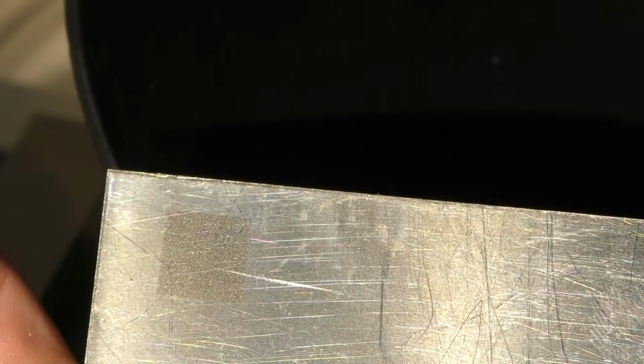Now look, I'm going to rotate this very slightly backwards and forwards, and as I rotate it backwards, it turns to black, and as I rotate it forward, I get the pattern back again, and then it turns to black. It's got a very narrow viewing angle, and that viewing angle is less than plus or minus 10 degrees. So I'm now going to go to the other extreme, and I'm going to put a 350 nanosecond pulse in, and we'll do exactly the same test. That's all I'm going to change is the pulse size.